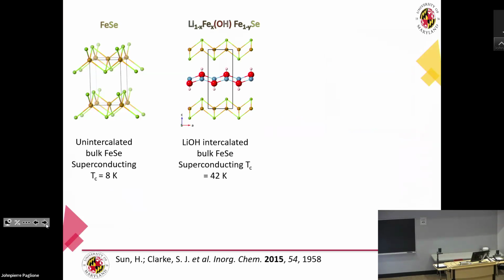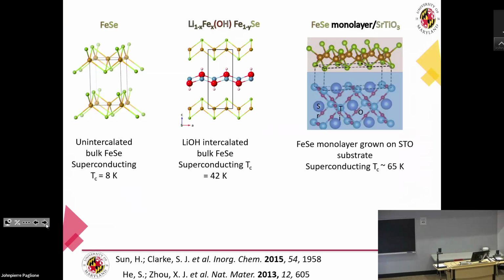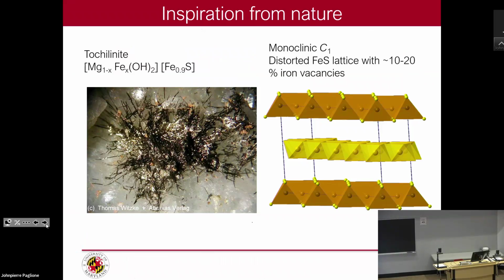I would say in the end, what we want to do, hopefully with these iron selenides, is can we break 42 Kelvin? Can we get something like 65 Kelvin? Obviously, it would be awesome to just get to liquid nitrogen, right? And so our idea is maybe we need to couple the iron selenide with some kind of layer mismatch, some other material that would strain the iron selenide. And so what we're doing is looking again at nature, which grows things hydrothermally. And we found this mineral called tochilinite, magnesium iron hydroxide with iron sulfide.